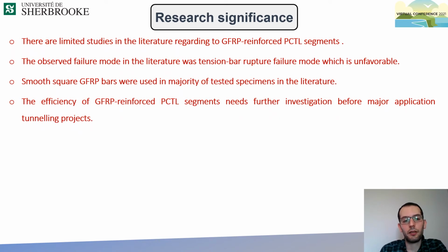There are very limited studies in the literature regarding GFRP reinforced PCTL segments. I can say that fewer than 10 specimens were tested, and the observed failure mode in the specimens was tension bar rupture failure, which is unfavorable according to the design standard. The smooth square bars used in the majority of the tested specimens in the literature are not recommended by the design standards. And we can say that the efficiency of GFRP reinforced PCTL segments needs much further investigation before major application in